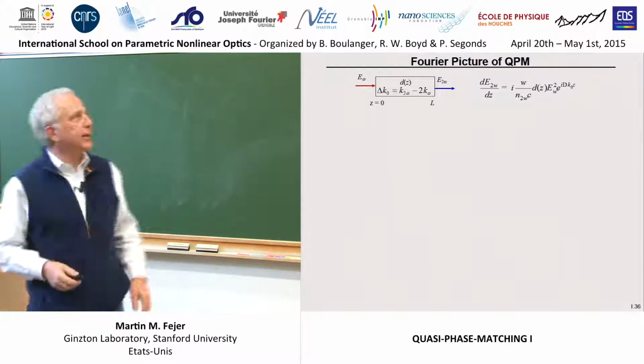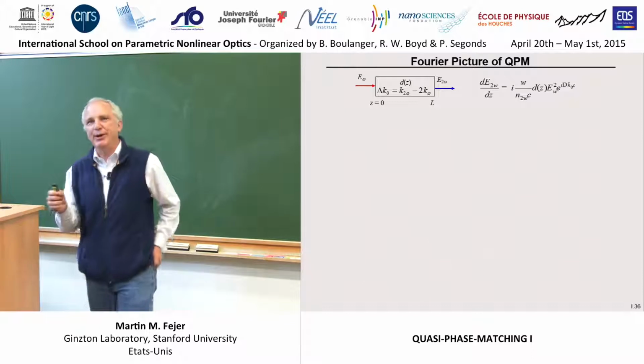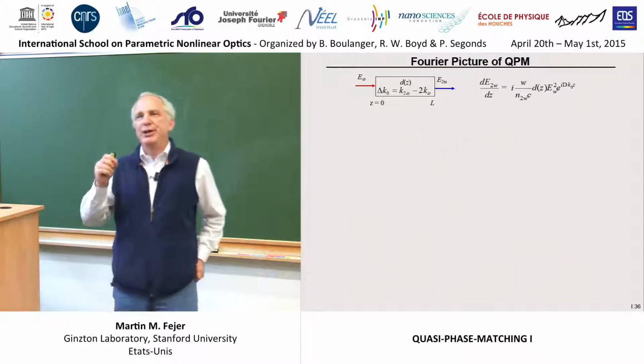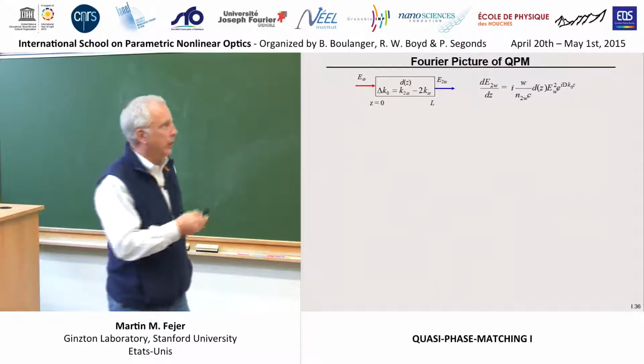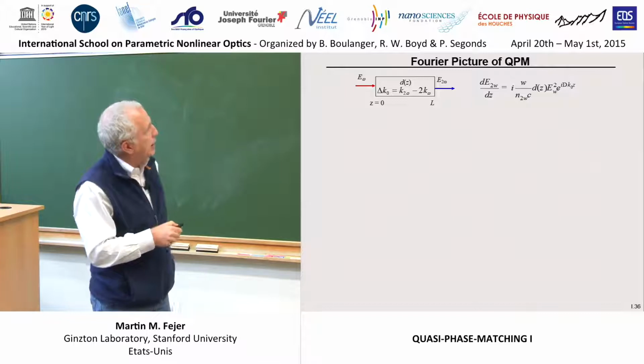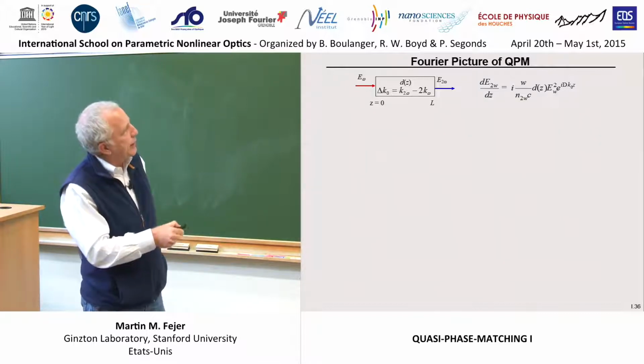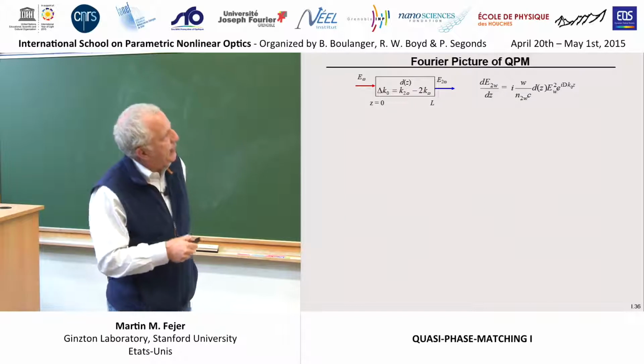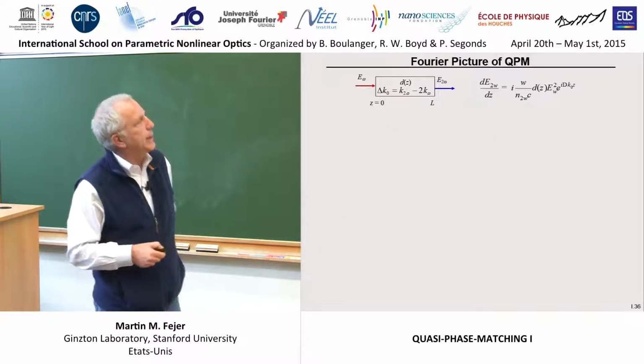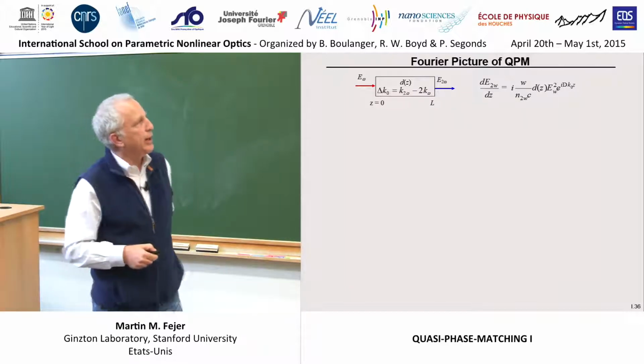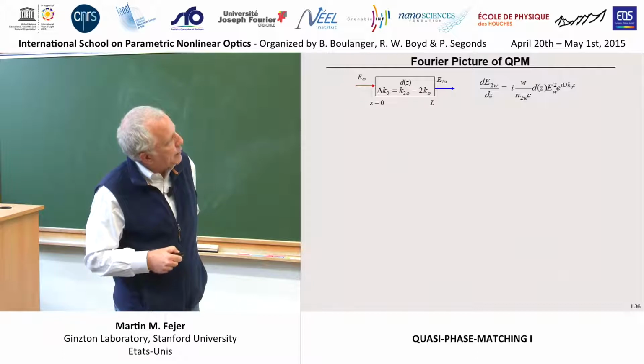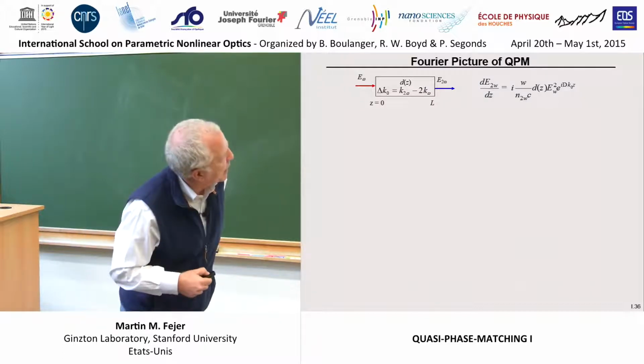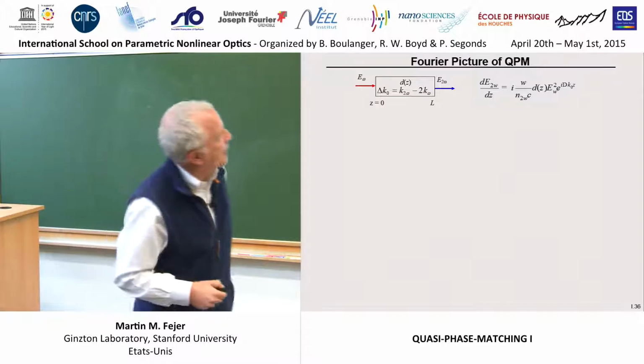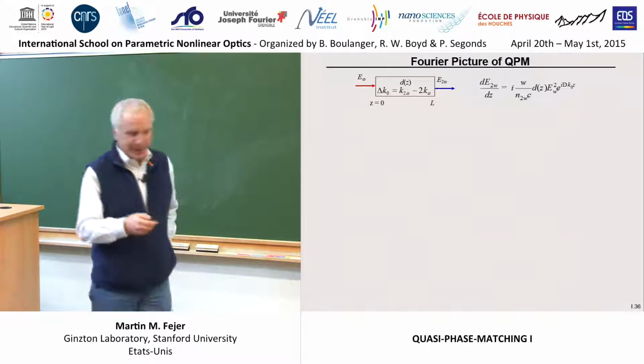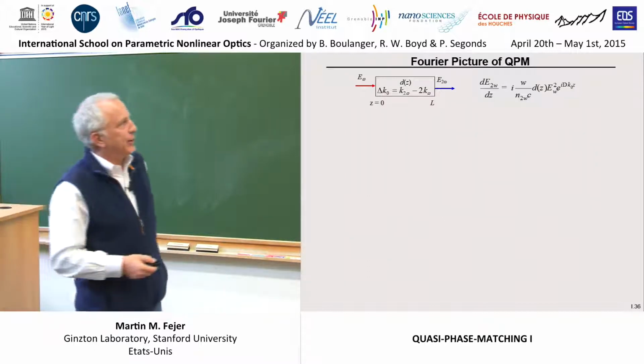If you don't listen to anything else in this talk, you should listen to this slide if you want to understand quasi-phase matching, because it's a useful heuristic picture that's actually quantitatively correct as well. So what's the basic model here? We've got a crystal of a certain length, a certain nonlinear susceptibility, and a certain phase mismatch. And we've seen from a few of our earlier talks that the evolution equation for the generation of second harmonic in that crystal depends on the nonlinear coefficient and the square of the input field, it should probably be E omega. Uh-oh, a few font problems emerged. I thought I got them all. French fonts aren't the same as American fonts, apparently.